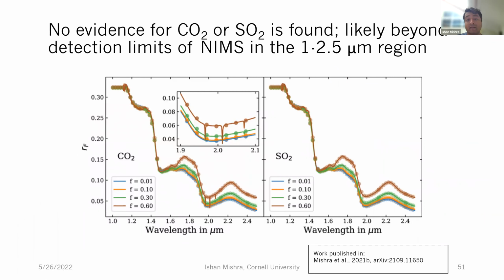Okay. And we didn't find any evidence for carbon dioxide and sulfur dioxide. And this was, again, expected because if you actually do the simulations of a simple water ice plus carbon dioxide or plus sulfur dioxide mixture, you need to go to unreasonably high abundance fractions of the oxide to actually start seeing the sharp features. And even then, they are so sharp that they fall within the resolution limit of the NIMS data. So here the dots present spectra binned to Galileo NIMS resolution. So basically it makes sense that we didn't see these features. And sulfur dioxide doesn't even show up at all. So in the 1 to 2.5 micron range data, which is basically the bulk of Galileo NIMS data, unfortunately, for carbon dioxide and sulfur dioxide, the trace oxides, it looks difficult that we'll ever be able to get something out.